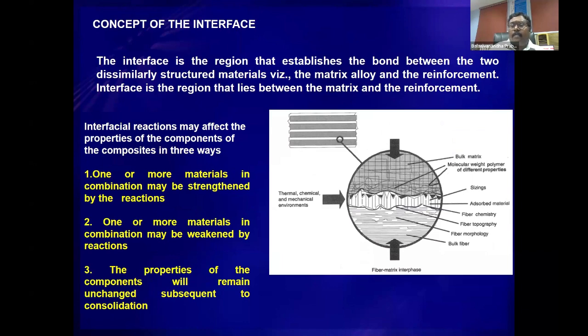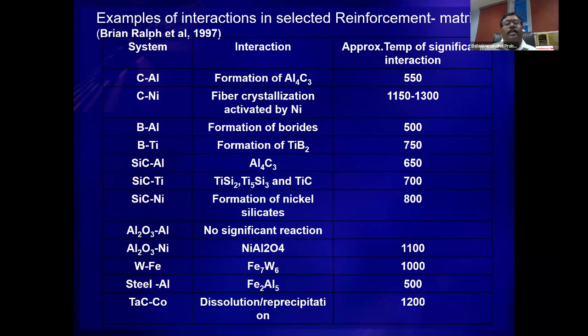See, the interface, as I said, is another problem, because the chemical reaction will induce a different phase formation at the boundaries of both matrix and reinforcement. So here, the possible reactions, especially when you have a different material system, most probably we take aluminum as a matrix material and silicon carbide or boron or carbon as the reinforcement. In these cases, especially in aluminum silicon carbide, we get a different product which is called Al4C3. It's a compound formed at the junction, a precipitate around the boundaries of the particle that stops the connection between the matrix and reinforcement, and also sometimes weakens the bonding at this junction. So for every case, you have some byproduct which stops the bonding between the matrix and reinforcement, and sometimes weakens the interfacial bonding because of the nature of the phases that are formed.